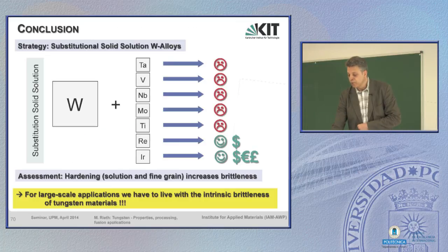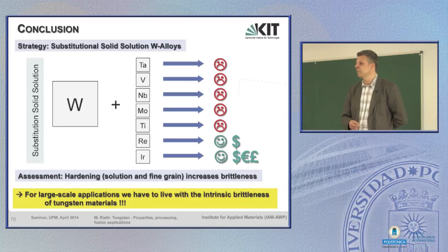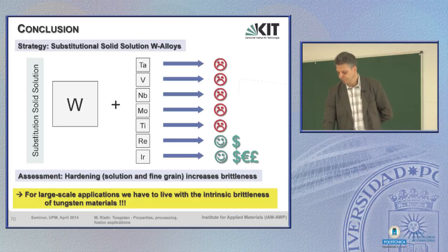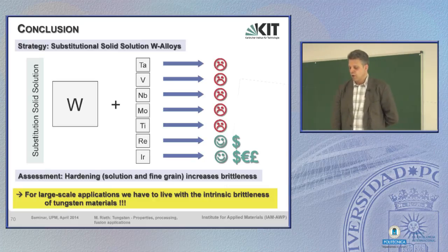investigation. And as a summary, if you alloy tungsten with a variety of materials, it makes tungsten even more brittle than it already is. So that's not a good solution. The only positive effect we know is on tungsten to ductilize is rhenium and, to a small amount, iridium, but these elements are so expensive that you cannot afford the material for fusion applications. So hardening by solution and fine grain increases the brittleness of tungsten, and for a large scale application as we would need it in fusion, we have to live with the intrinsic brittleness of tungsten. This is the main conclusion and result.